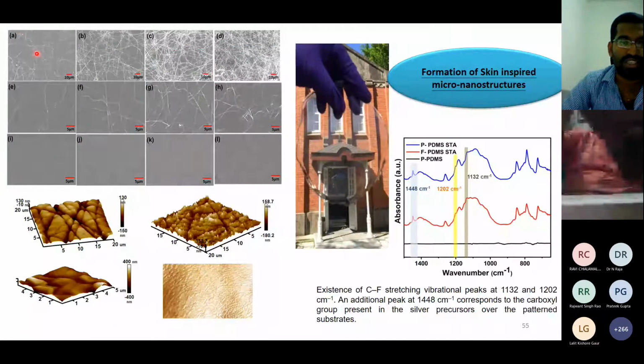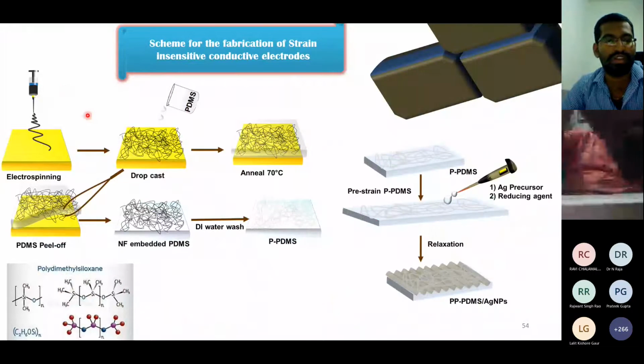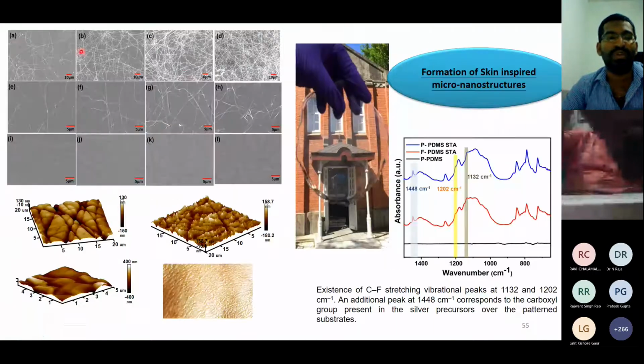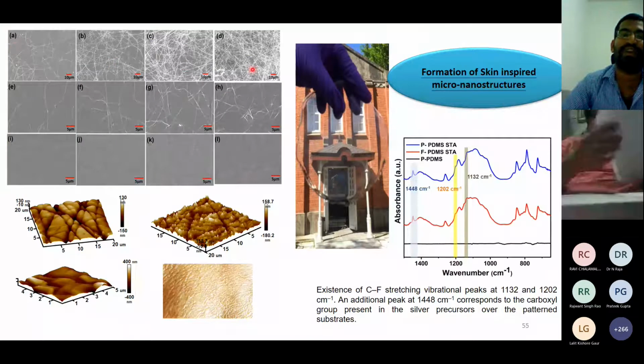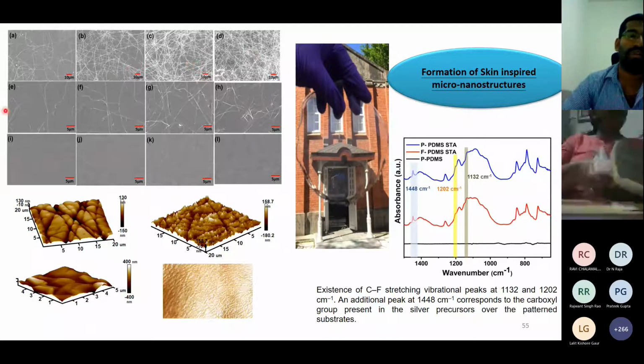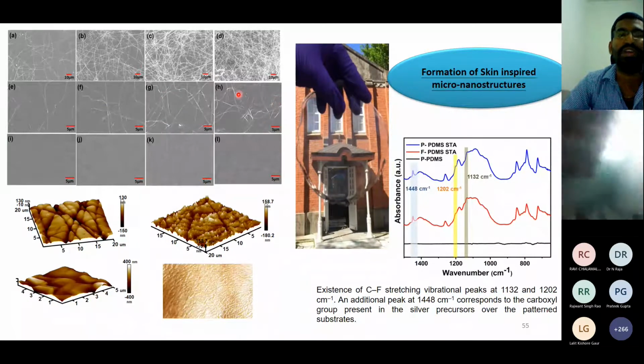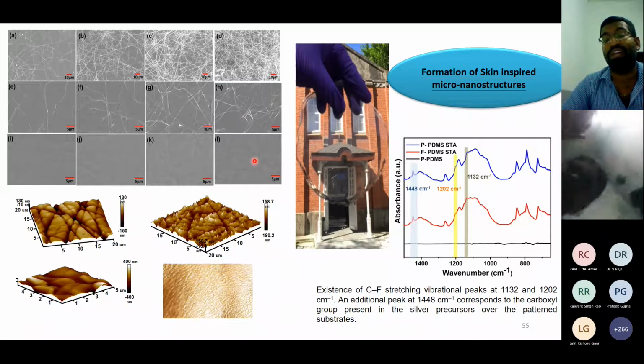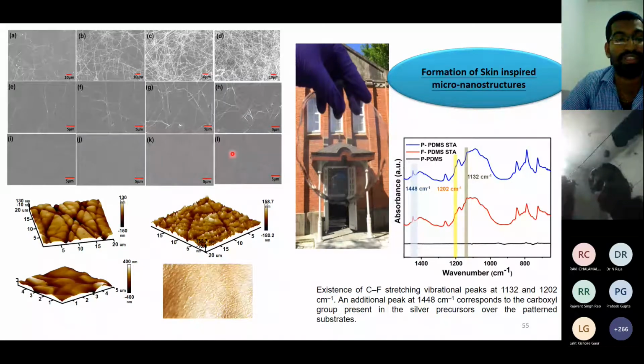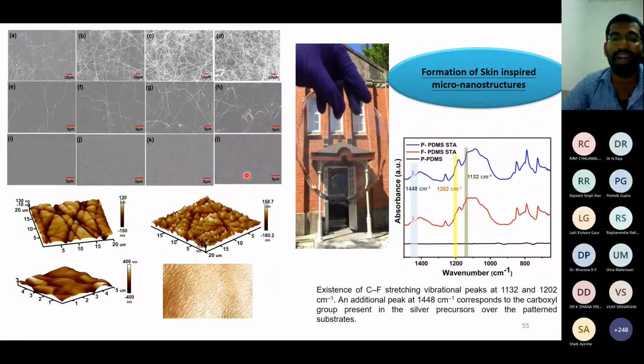So here, these are the SEM evidences for this process. I said how we do this and then how we etch this. So in the initial case, we just embed the fibers like this with different timings to form different dense nanofibers like this. So now we peel them, and then here we can see a few nanofibers on the surface. The others are getting embedded, so that will give rise to good mechanical properties as well. And then we etch them, so we will be ending up with this kind of nano ridges.